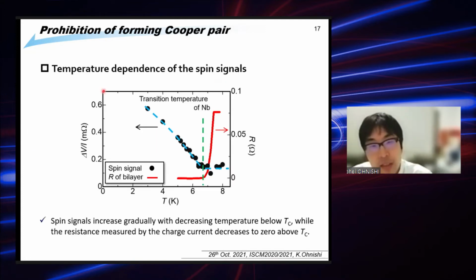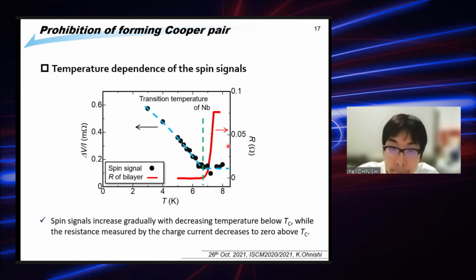Moreover, we measured the temperature dependence of the spin signals. From this temperature dependence, we can see the gradual formation of the superconducting gap at the interface below the TC. I'd like to emphasize that this result indicates the pure spin current can be a good probe to estimate the superconducting gap at the interface, even in the interface inside the samples. Okay.